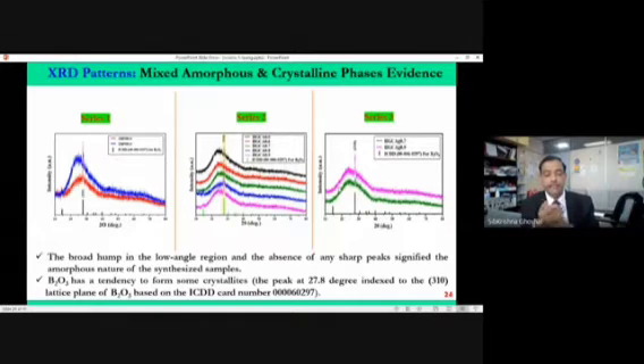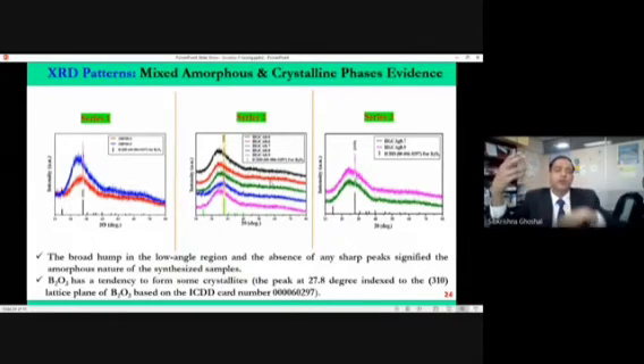How do we know? Another proof that this material is glass and crystallite together. That means in the background of the glass, the majority is glass, but there are little crystallites in the material. So we have seen that there are sharp peaks in the X-ray diffraction. We'll also do Raman, we'll also do XPS to prove further, because only one investigation will not be enough. You have to cross-correlate, bring other cross evidences to reaffirm that this is really true. So these are basically the X-ray data.